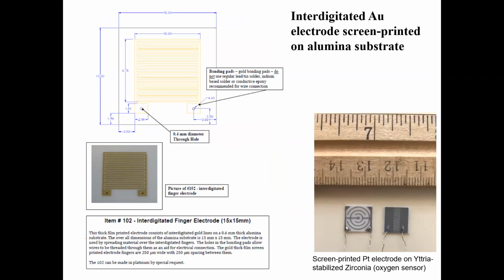So in terms of the substrate that I talked about, here is a piece of alumina where you create this interdigitated gold electrode by screen printing, and you can create the mask. And you can see in CAD, CAM, you can draw this, and you can specify the width of the finger, you can specify the distance between fingers, and then you can screen print using a gold ink through a mask that looks something like this. And it comes with two holes, and this one set of fingers will be connected to this pad. The other set of fingers will be connecting to that. And you can attach your lead wire through these holes and connect those lead wire to the measuring device.